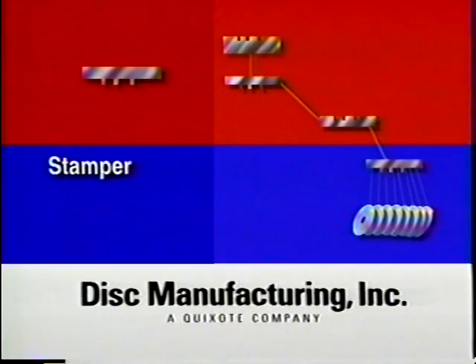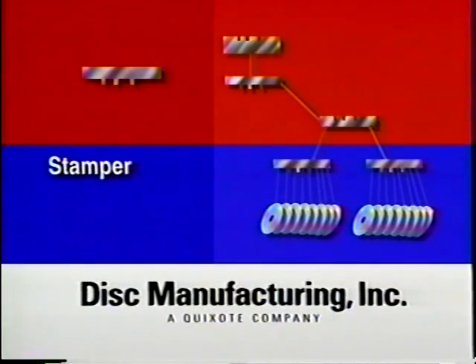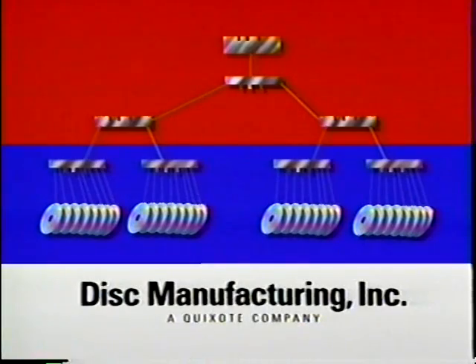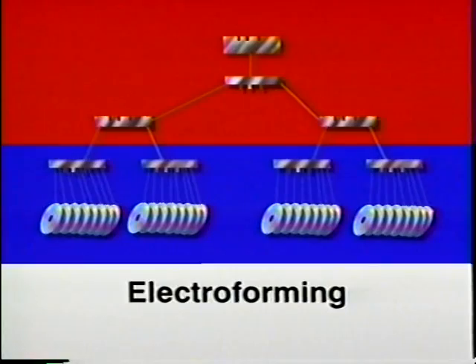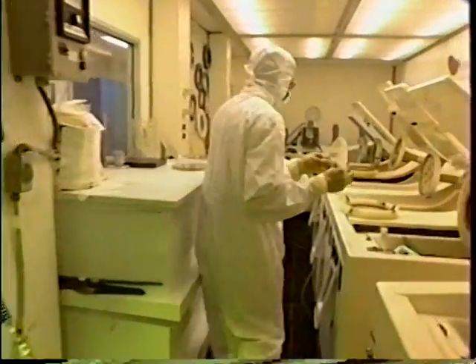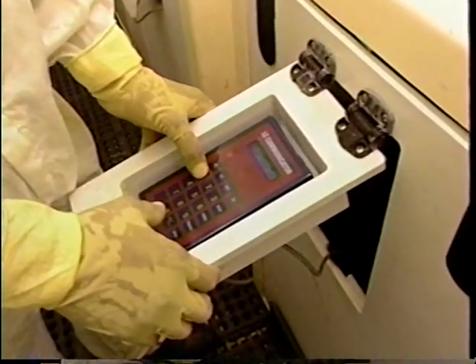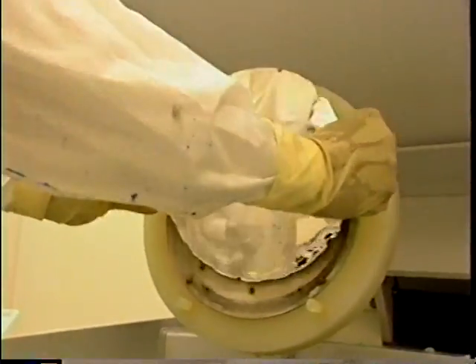It's from this stamper that the compact disc actually packaged and sold is formed. Thousands of discs can be produced from each stamper, and if a stamper wears out or if additional ones are needed, it may be formed from the mother. If a disc's popularity demands it, a father can be used to grow another mother to make more stampers and more CDs. This family tree of generations is literally grown in a process called electroforming. It all takes place in a series of chemical baths. The silver-coated glass plate is placed on a rotating back plate and submerged in a nickel solution. When an electric current is applied to the solution, the nickel is deposited on the silver of the glass plate. The process takes over two hours. Afterwards, the nickel layer is peeled away from the glass. This same electrochemical process is used again to create all the generations needed for mass production.